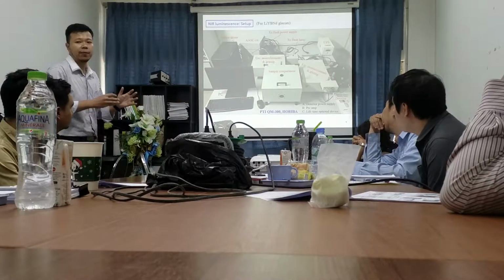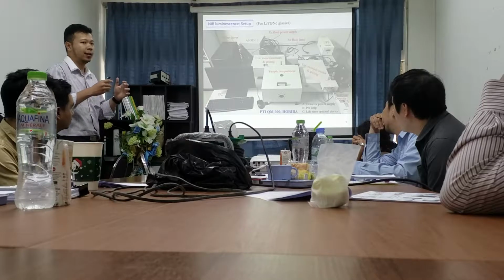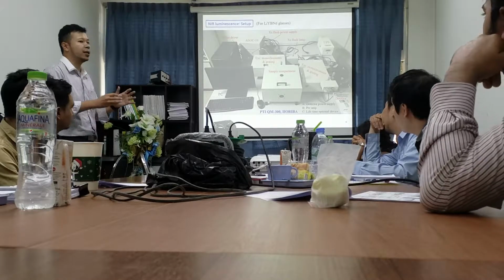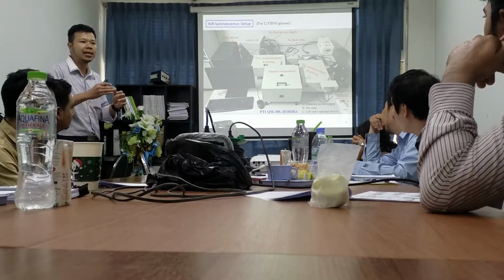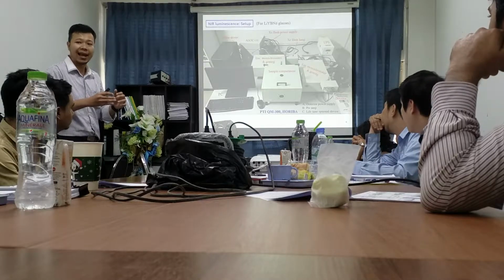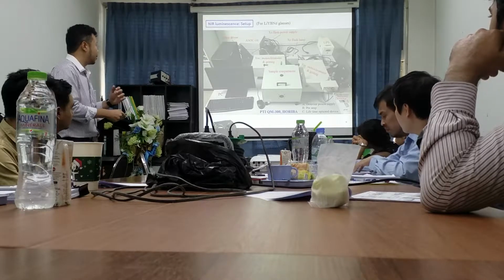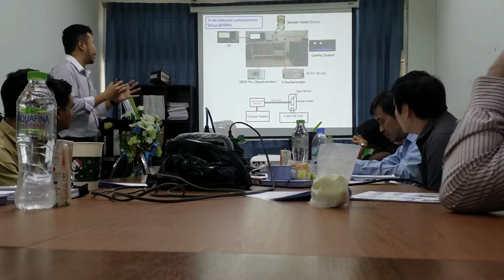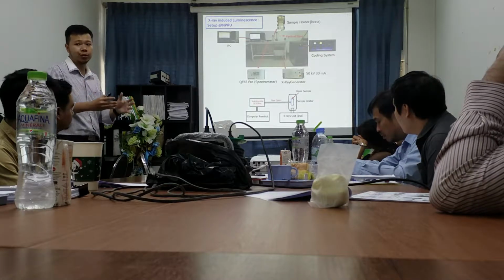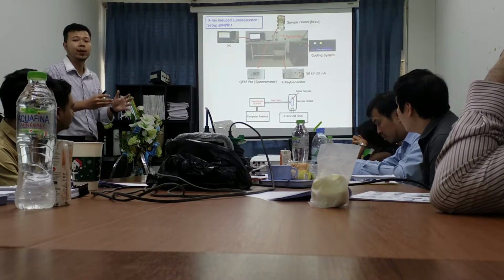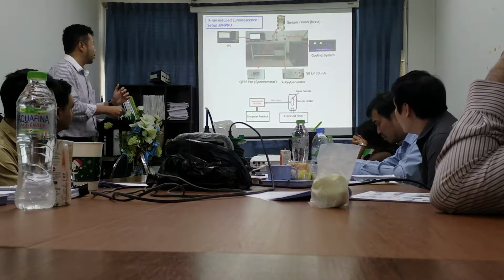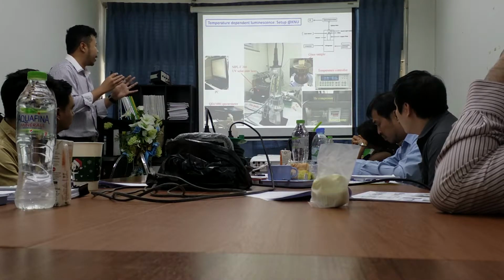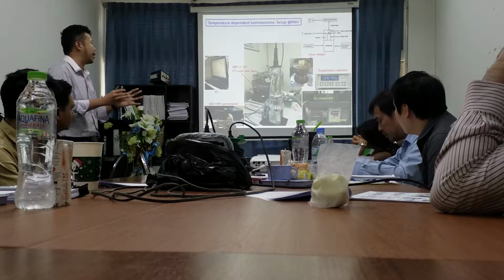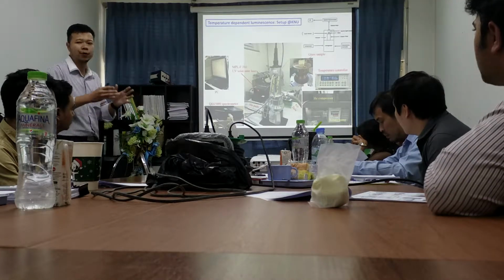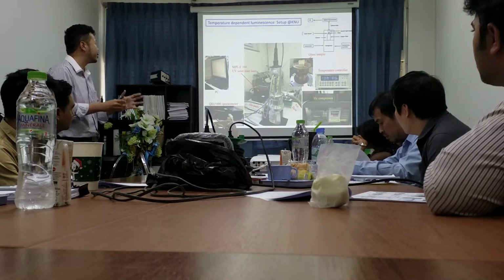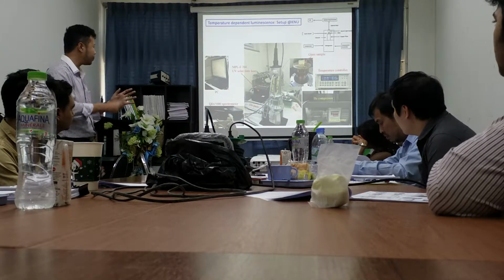This is the experimental setup in the glass lab to measure the emission spectrum in the near infrared region of the Nd doped glass. And this is the experimental setup here also to measure the X-ray induced luminescence spectra. And this is the experimental setup at the Korea National University to measure the temperature dependent luminescence.